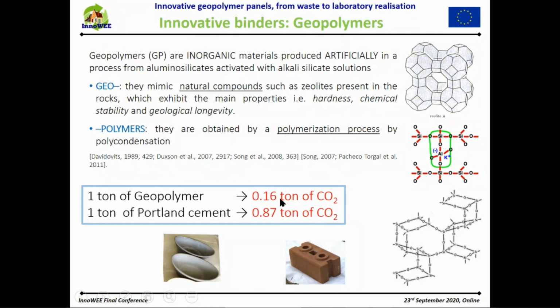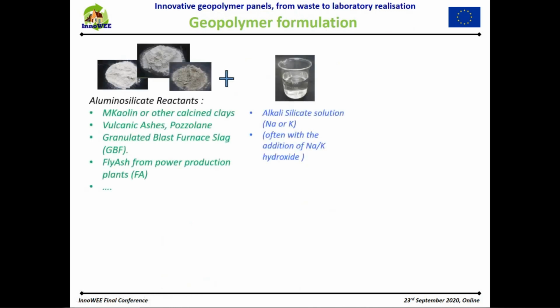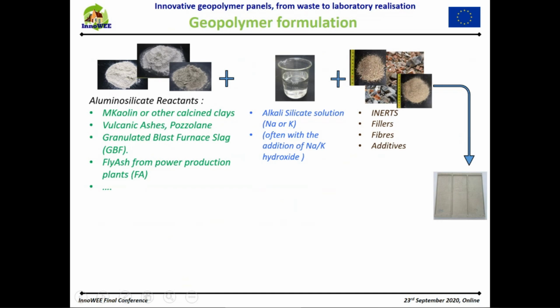The reagents to produce the geopolymers are aluminosilicate and an alkaline solution of potassium or sodium. Aluminosilicates used also in our project can be clays like kaolin, calcined as metakaolin, or slag wastes that come from the iron production process, or fly ashes, other wastes from energy production plants. Other aluminosilicates are pozzolans, very common. To these reagents we add inert materials, in our case construction and demolition waste, and the mixture produces a liquid that is poured in a mold to produce the geopolymer material.